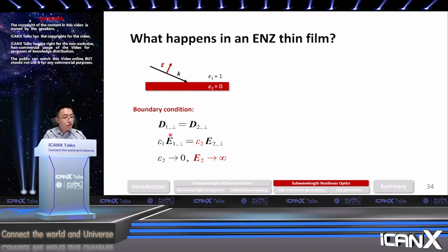And the displacement field can be written as the permittivity epsilon times the electric field E, right? In air, we have a finite epsilon 1 and E1, and if epsilon 2 goes to 0, does that mean E2, the electric field inside this ENZ material, is going to approach infinity? That means we'll get a huge enhancement of the light-matter interaction that can potentially boost our nonlinear frequency conversion process. Of course, anything that goes to infinity seems quite questionable, right?